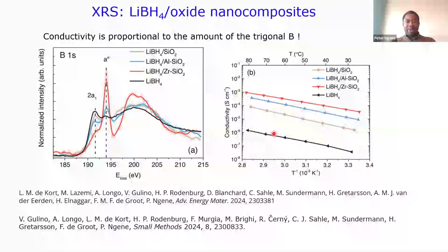So this is the bulk-like ionic conductivity. If we now put this in just silica, this is what we have, and we can see here that it has less composition. If we put it here in aluminum-modified silica, we can see we have more of this trigonal boron-like material. And then when we now put it on silica that is modified with zirconia, the same amount, the same surface area, we do see that the concentration of the interface composition is much higher here. And then the conductivity is also high in this case.